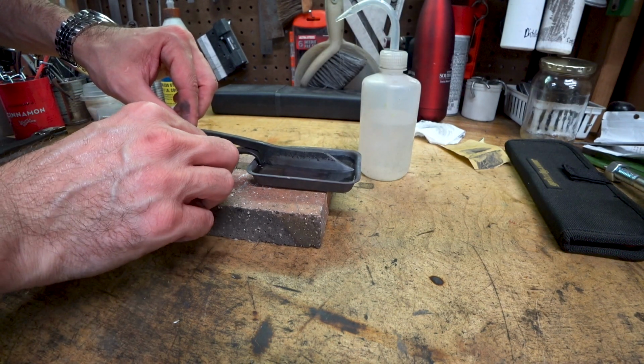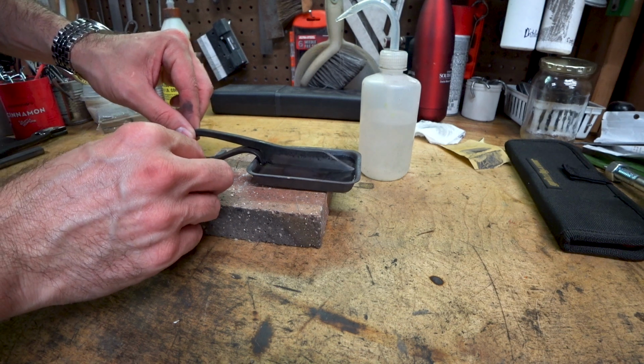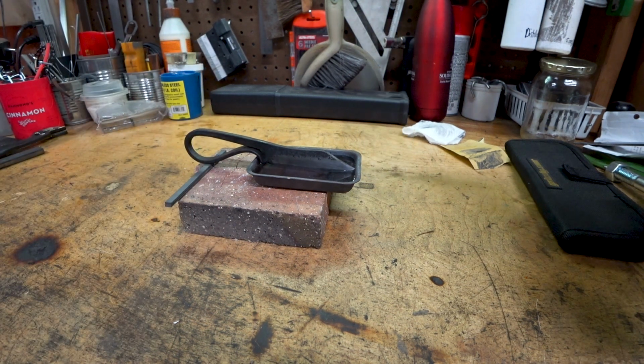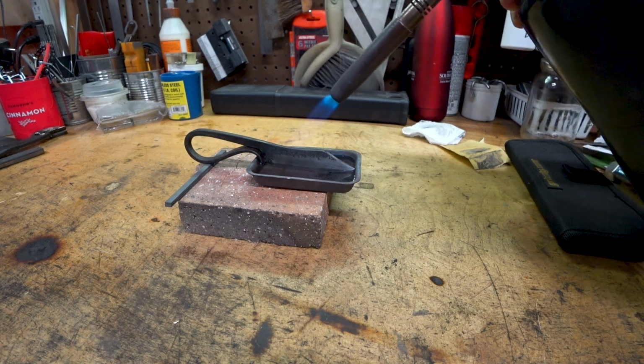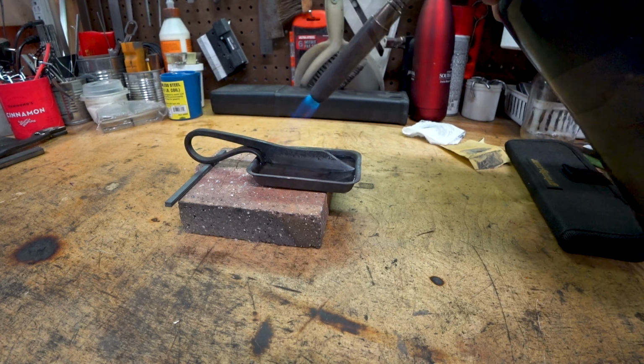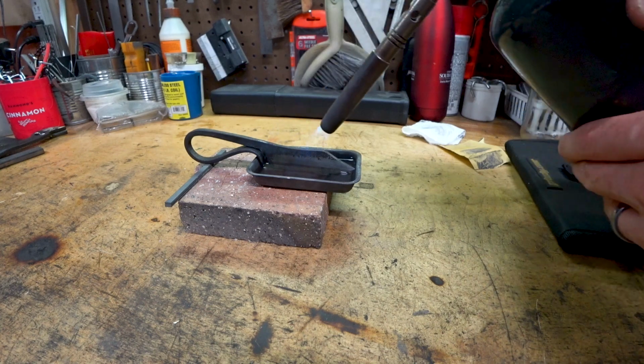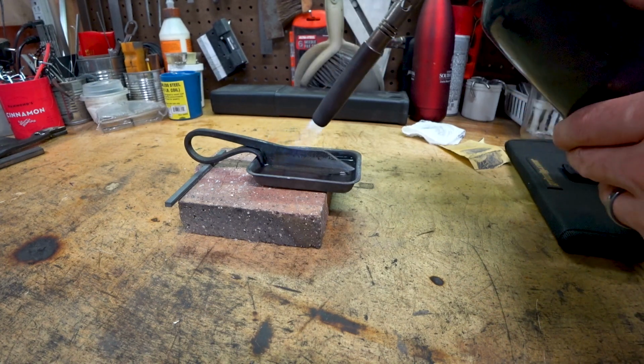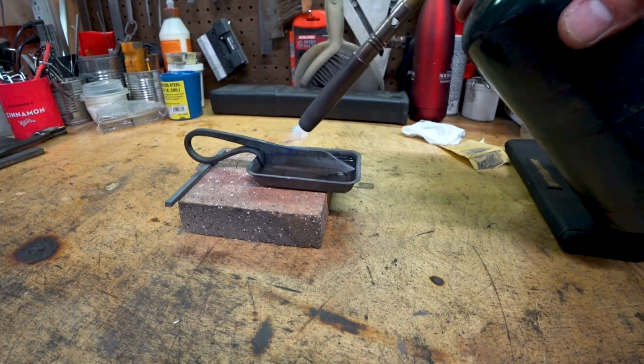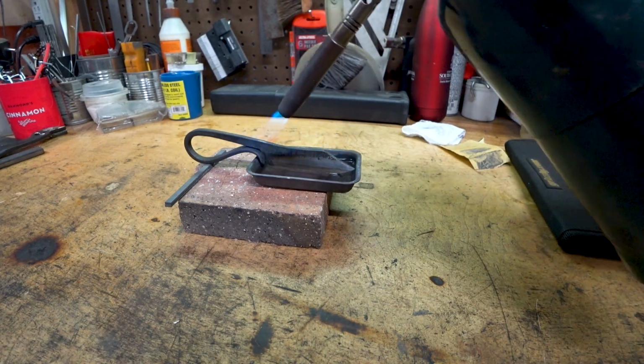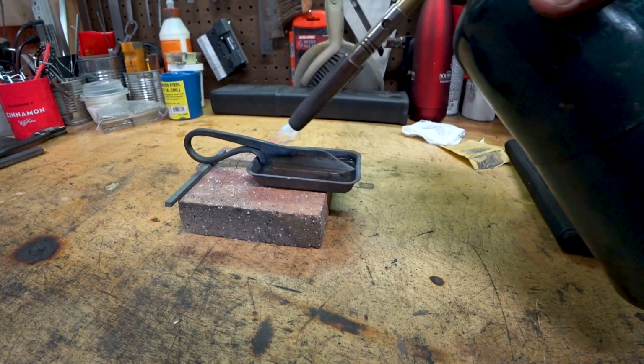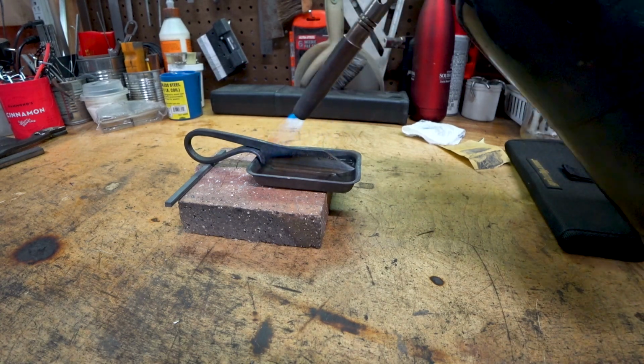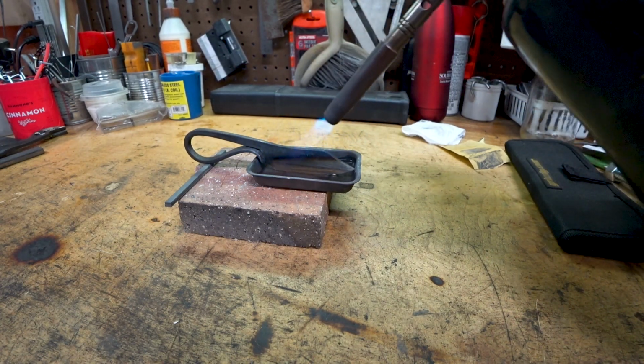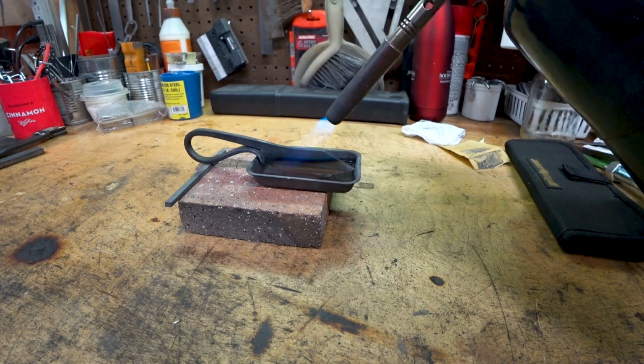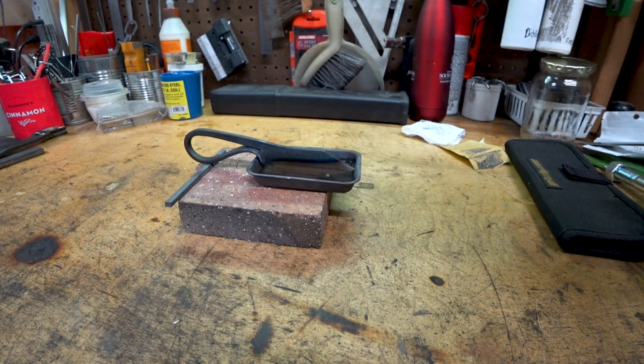So what I'm doing here is dunking the edge in water in a little steel dish. This is a magnetic parts tray that I just pulled the magnet off of. Next, I'm going to heat up the spine and the base of the handle and temper it back further. This will give me a softer, tougher spine and handle and a nice hard edge. And the water just keeps you from over tempering the edge. So you can see those temper colors creeping down the spine, but we're not actually tempering the edge back any further because the water is constantly cooling it. And so this is a way that you can get a good selective temper.